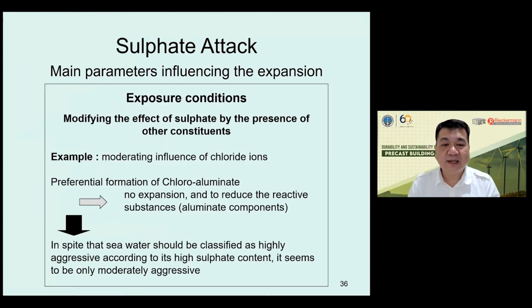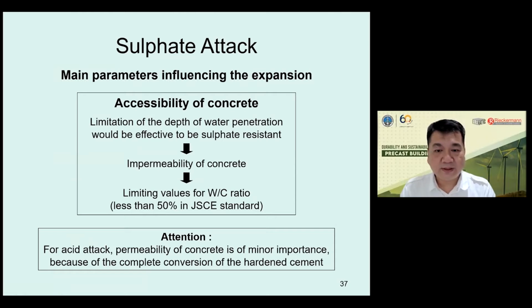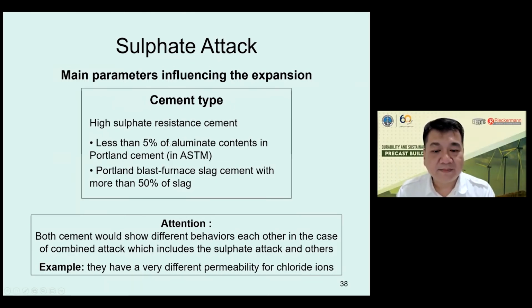So yeah, sulphate attack. Mainly, we can reduce the sulphate attack by using low aluminate cement. So this is actually the basis for the cement in the marine environment. So yeah, a limiting factor is the water to cement ratio. We reduce it to 0.5. So this is the Japanese standard. So this is the sulphate attack. And then, yeah, cement type. Sulphate attack is a degradation factor in the concrete. Because for acid, we try to protect against it. But for sulphate, we still have buildings that are exposed to sulphate.